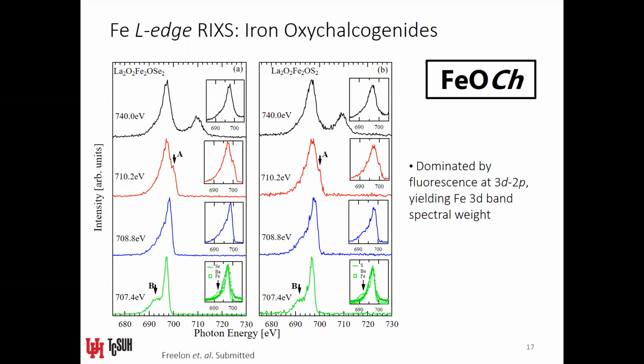And in particular, there are a few features to point out. The large mass that you see, for example, in the selenium version of the Mott insulator and the sulfur version of the Mott insulator, those large mass represent the main 3d iron band. And at some of the energies that we use, for example 707.4, these energies are taken close to the absorption edges, and we see these extra features. These hump-like features are examples of lower Hubbard bands.